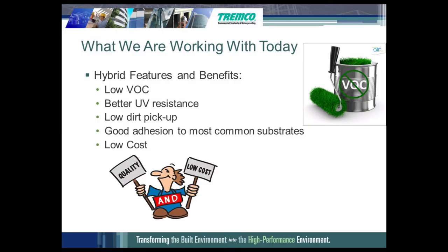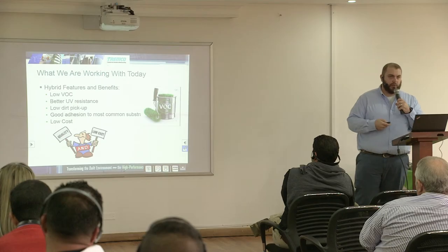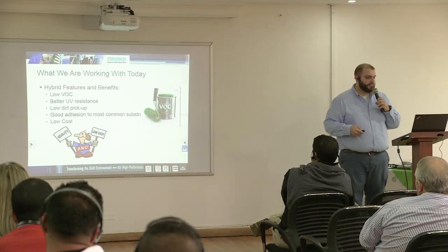Some of the features and benefits of this: they're typically cheaper than silicones, more expensive than urethanes. They are the lower VOC end of the products. You have better UV resistance than most urethanes, but not quite as good as the silicones. You have low dirt pickup. Dirt does not stick to it. You have good adhesion to most common construction substrates. You can adhere to glass, you can adhere to concrete. It's very versatile. And as I said, on the cost spectrum, you're in the middle. You're not at the higher end of the silicone or the lower cost end of the urethane.